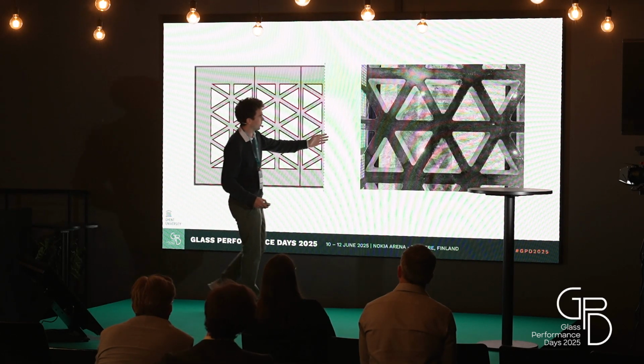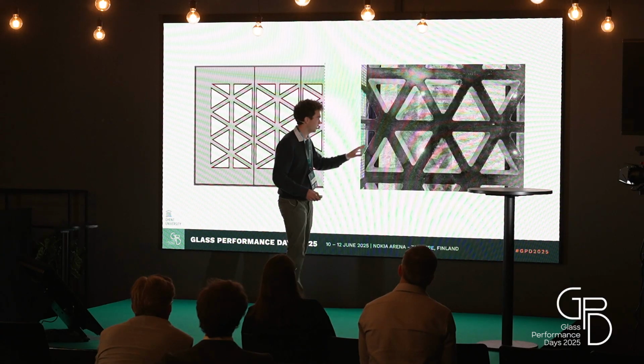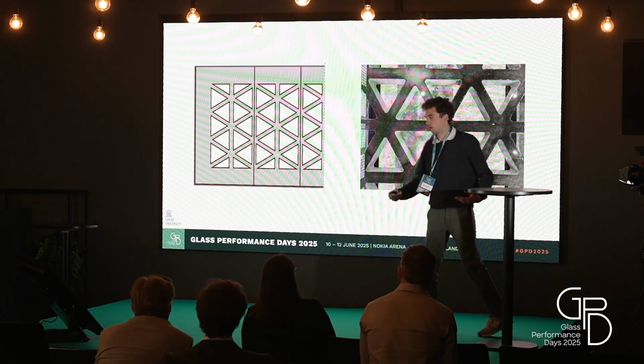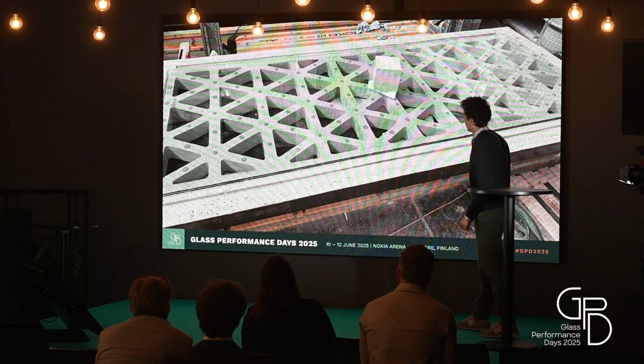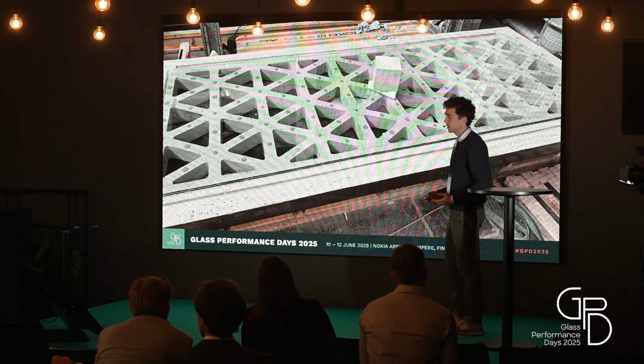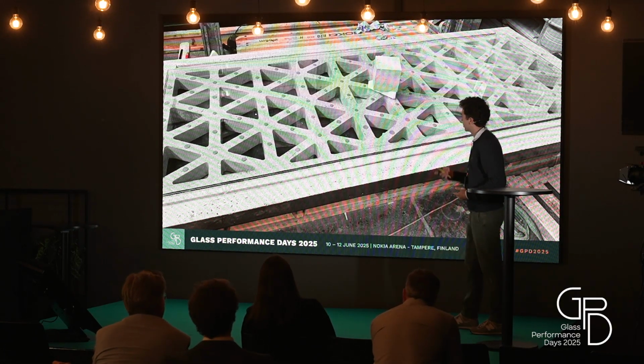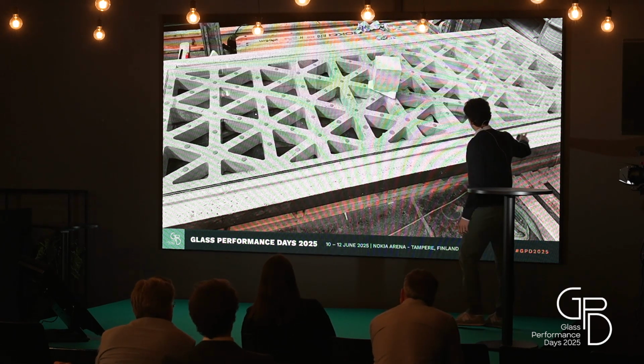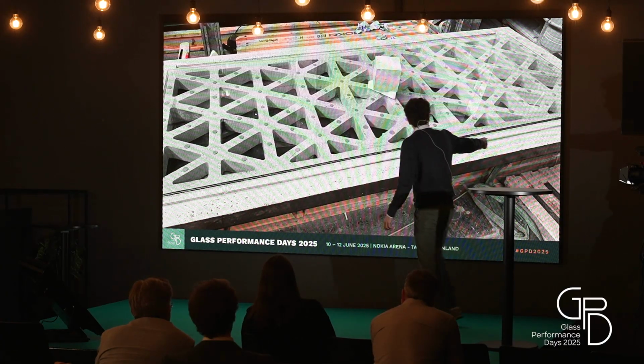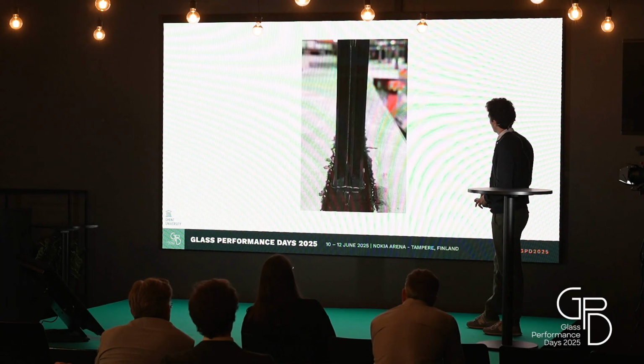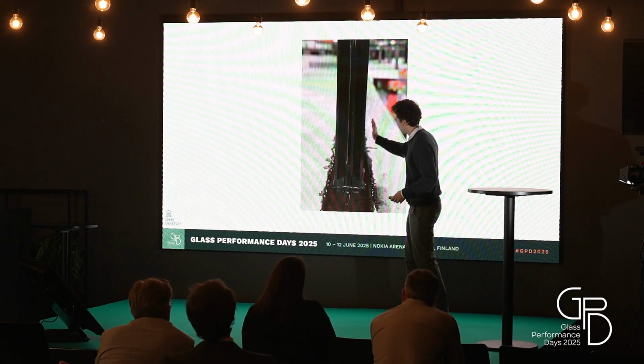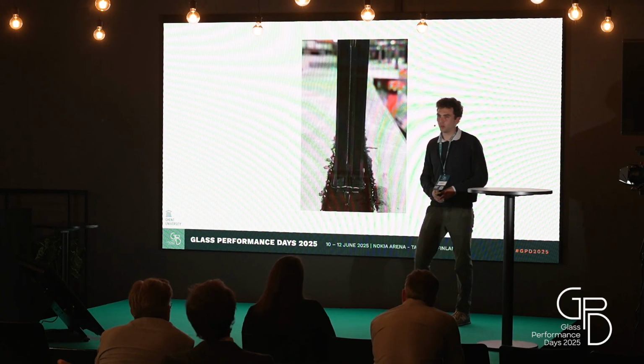And this is then the result after bonding, so you can really see that the tape and the transparent epoxy are one visual element here. Then at the bottom side of this hybrid panel, we used a different technique, more with point fixings, not the full area bond. Therefore we used an epoxy that had a higher viscosity to make these dots before placing on the glass plate. And as a last step, you see we have the slot already made for the T-shaped beam, the glass fin that comes in. We just placed the glass in the slot, then filled the void with epoxy and let it cure.